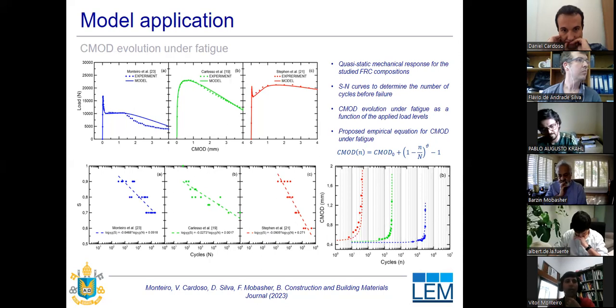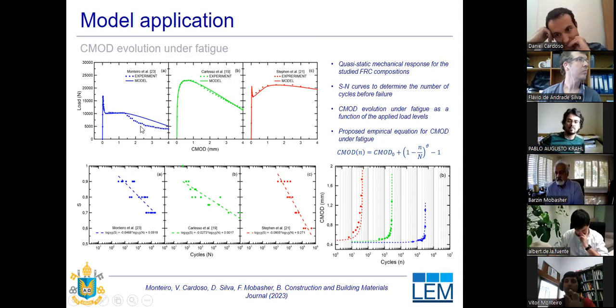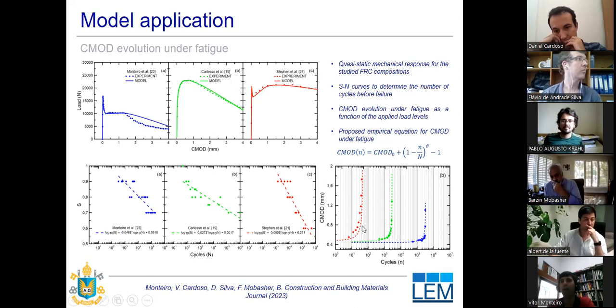So we have here for the three studied authors a good fitting of the analytical equations for Cardoso, Stephan, and Monteiro. We could verify a good fitting with the experimental results, and so the closed form solutions are done for the quasi-static behavior. The next step is to verify using as input for the model the SN curve. So we have the SN curves for the authors. And the next step is to evaluate how CMOD evolves along the fatigue life.